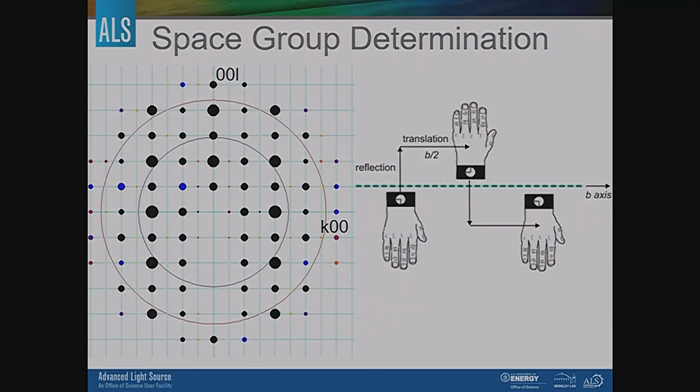That's a great question. So, in here, nothing there, right? That has to do with actual diffraction real space geometry. We can't always access all the spots. So probably the most likely reason there are no spots here is because that's an area that was inaccessible with the diffractometer, with relationship to how the crystal was mounted and how we can move. That's on a 3-circle diffractometer, and there is some definite dead space that you can't get the crystal swung around to. So that's probably what that is.